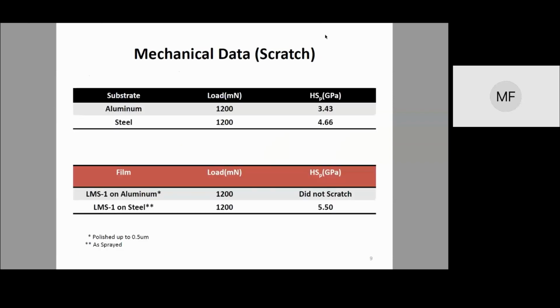I also conducted scratch tests on the aluminum and the steel samples with loads of 1200 millinewtons for each. The substrates scratched at, for the aluminum, was about 3.43, and the steel was about a gigapascal harder, which was to be expected. The films, however, the LMS1 film on aluminum was polished up to 0.5 microns using a diamond